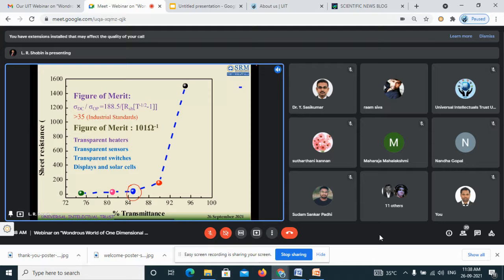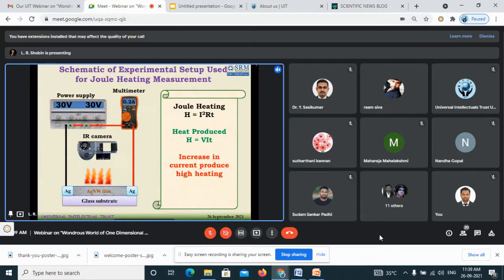So these films have a good figure of merit also, which is the industry measure for transparent films. If you have a figure of merit greater than 35, you can easily go for industrial applications like thin film fabrication, solar cell fabrication, heater fabrication, display fabrication. So what they will ask for is a figure of merit of 35. Here it falls around 101. We are hitting more than 100. So these films are industrial standard films, and you can go for industrial applications also.